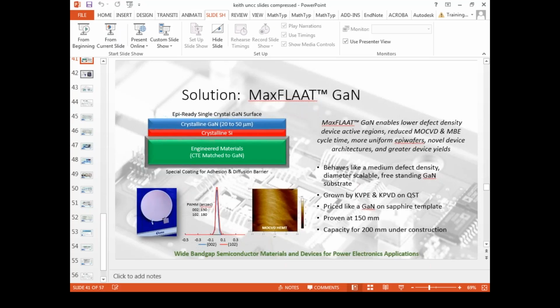So we have the freedom to add another 10, and we're working on 100 microns. In fact, we're working on growing bulk on there. And if we can do that crack-free, the defect density drops with thickness. I don't have that slide, but we're able to. So I think we're already an order of magnitude lower than any GaN on silicon power device out there by just doing this, if not 2 orders of magnitude.